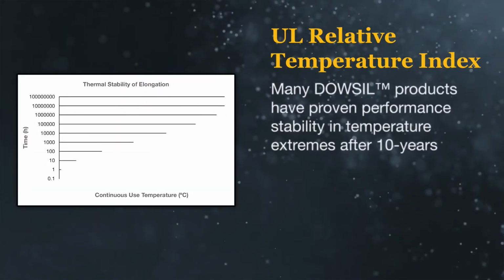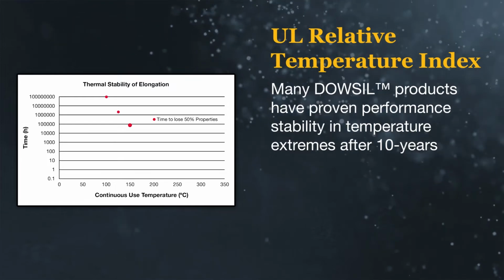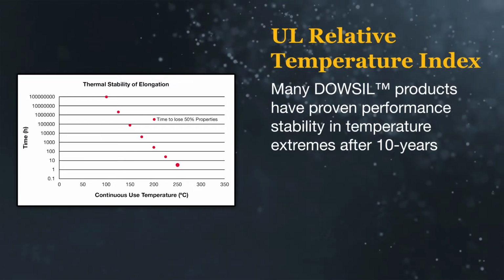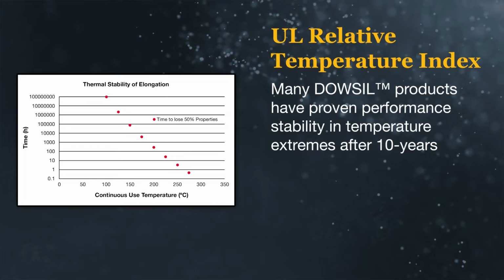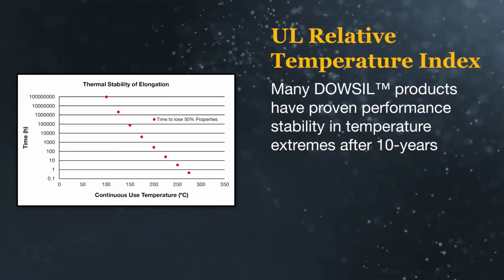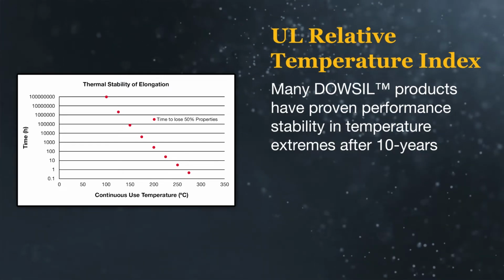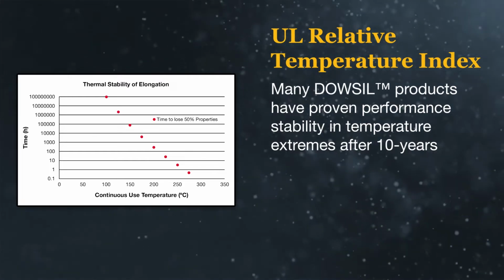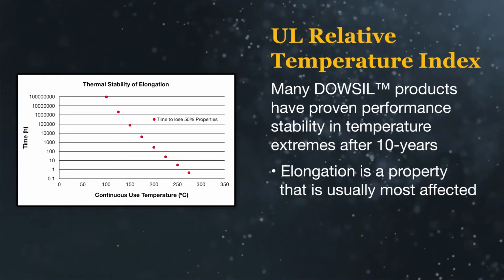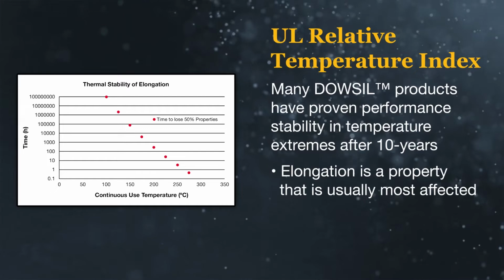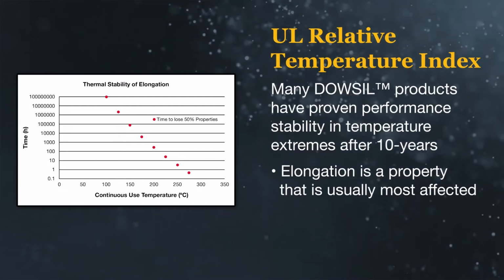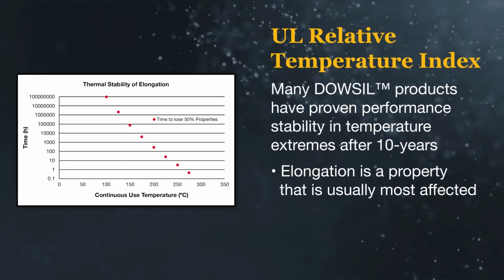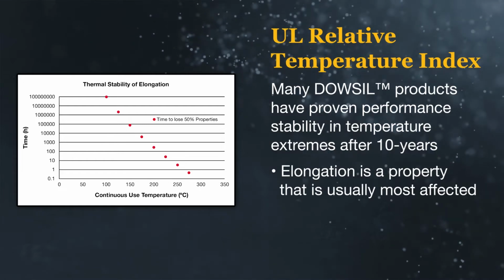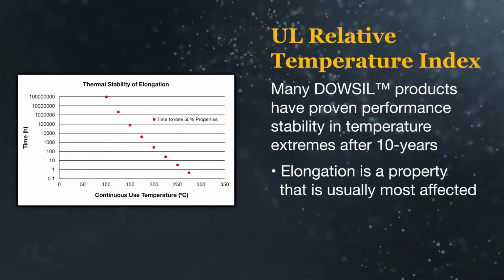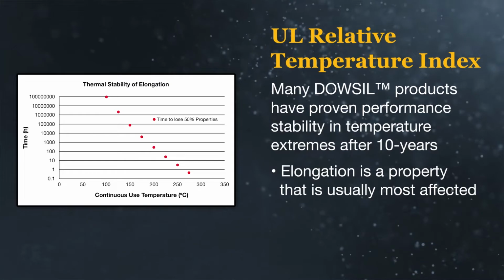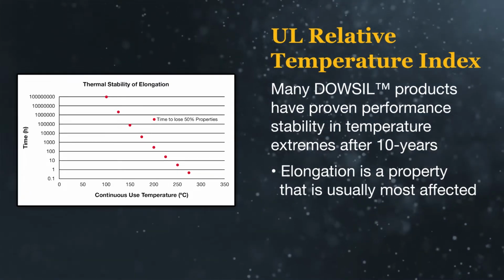At Dow, many of our TDS upper temperature limits are based on UL relative temperature limit testing and represent an expected 10-year life at that temperature while maintaining at least half of the product's original properties. For silicones, this typically means retention of at least half of the original elongation. Actual use life may be longer than 10 years, depending on application requirements. If shorter exposure times are needed, the use temperature can go substantially higher.